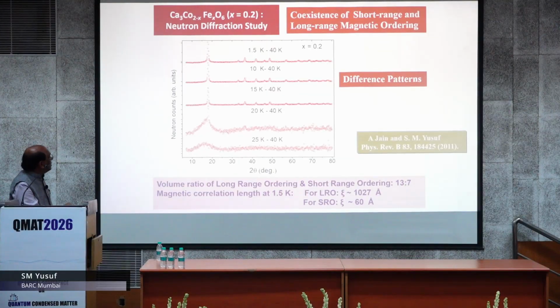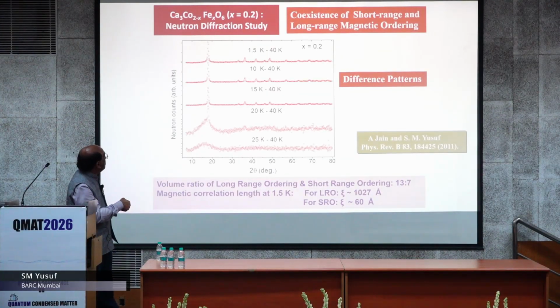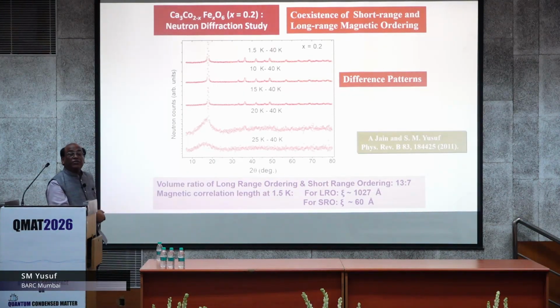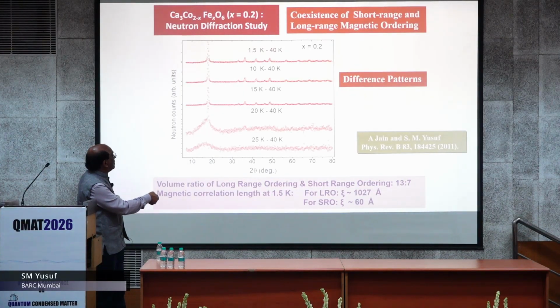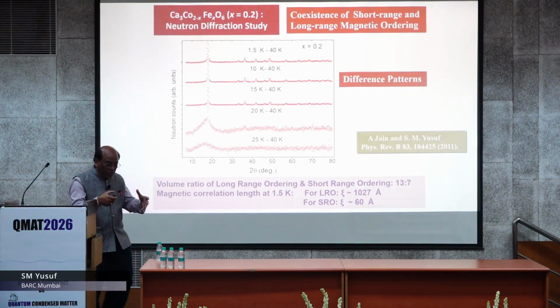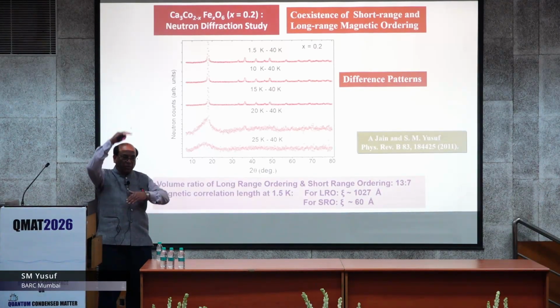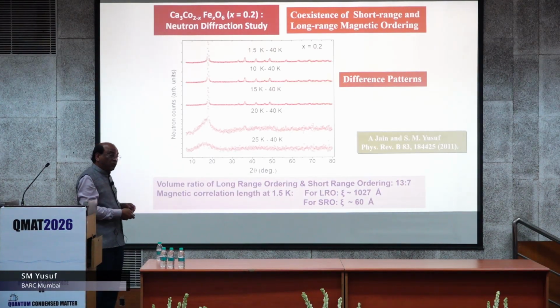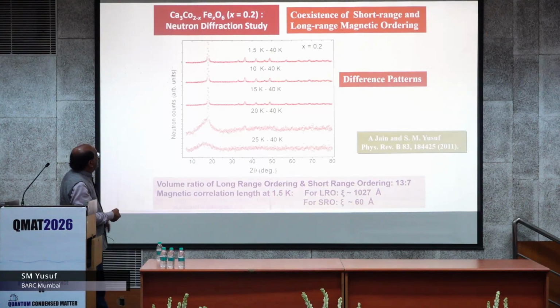Even in one of our earlier studies, what we also saw in the same series, same kind of structure, the magnetic ordering, of course, partially disordered antiferromagnetic Bragg peaks appear at low temperature, but above the so-called TN, the formal TN, we do see short-range magnetic correlation, and that is another hallmark of this frustrated system. So these are beautifully captured by doing neutron diffraction. We have subtracted the nuclear Bragg intensity, so only the magnetic intensity is seen. So this is the spin-spin correlation above the magnetic ordering temperature, which means it is in the so-called paramagnetic state.